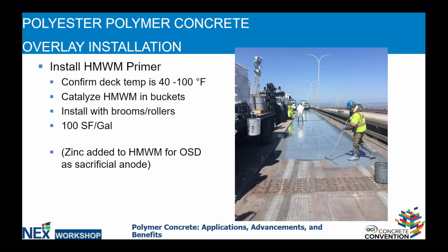When the primer is applied, as you see in this photo, the primer is a very low viscosity, high molecular weight methacrylate primer. It's mixed with a catalyst and then basically poured out, spread very generously across the prep surface. And what I ask for in terms of a prep is a sandblast or a metal shot blast type of prep. If you're familiar with the concrete surface profile number convention, a CSP of 3 is very typical.